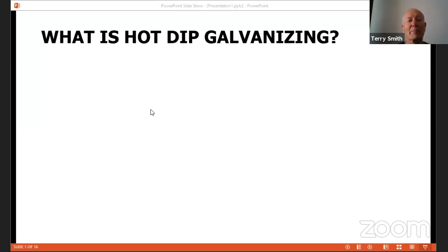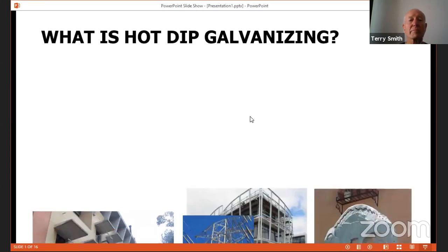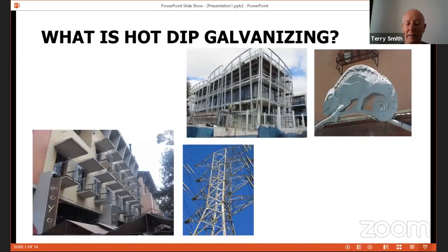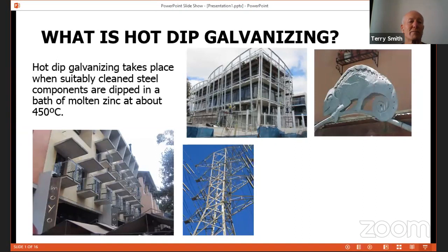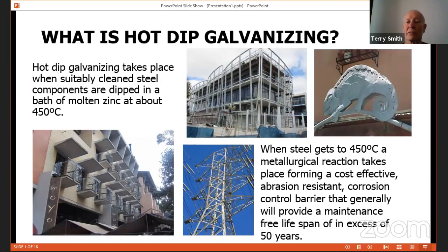Ladies and gentlemen, I'm going to talk a little bit about hot-dip galvanizing, as you heard. We asked the question, what is hot-dip galvanizing? Hot-dip galvanizing happens when you take pre-cleaned steel and dip it in a bath at 450 degrees C. Zinc melts at about 419 degrees C. When the temperature of the steel reaches 450 degrees C, a reaction takes place, giving you an abrasion-resistant, cost-effective coating, which will last at least 50 years in the atmosphere.